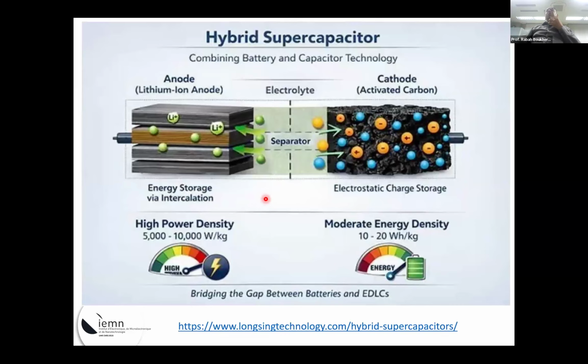So this is an example which I found again on this company's website. They take exactly the known things where you have the lithium ion anode and you have activated carbon on the cathode. So definitely you can improve this by playing here with the carbon. If you can develop much more effective and efficient materials, it would be even better, but this also works already very, very nicely. And you can see you cannot reach the energy density of the lithium ion batteries, but definitely can improve this compared to that of the supercapacitor.